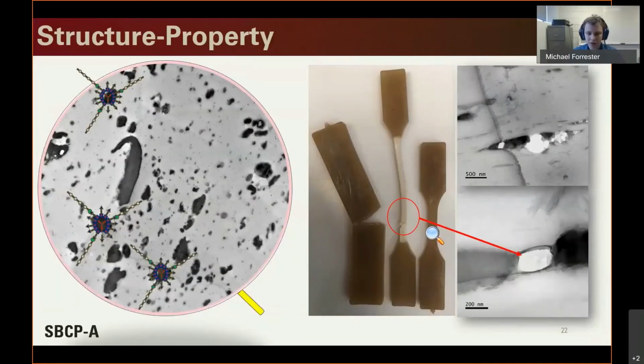So this was really promising. One of the things that we wanted to look at is whether or not we were actually doing what we thought we were, and making sure we could explain those mechanical properties. And so we looked at some of the microscopy. And the TEM definitely seems to suggest that yes, we are getting some of these nice micelles to form. And then on the tensile bars, one of the really cool things we saw is that you get these beautiful cavitations of the rubber domains as you start to stretch them. And that's one of the things that's pretty well known in the literature, that if you can get these good cavitations, you can get some really impressive mechanical properties, and that's what we saw here.